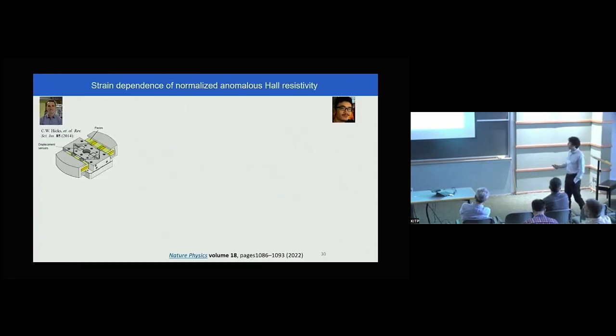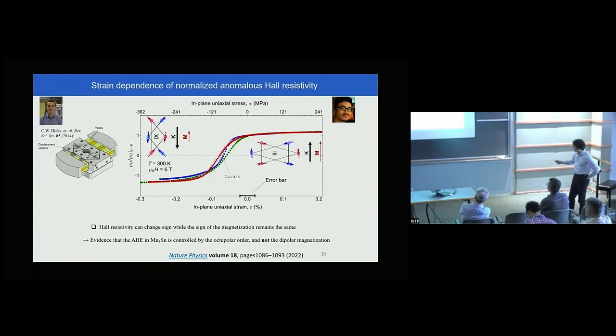Collaborating with Cliff Hicks at that time in Dresden, he moved to England, he developed this very nice piezoelectric cell, which allows us to go to tensile and compressive stress on both sides continuously, and within the elastic limit, we did this measurement very continuously without any problem, and reproducibly. And you can see that this is a renormalized Hall effect. The plus sign goes to the negative as a function of uniaxial strain. So this is exactly what you expect for the anomalous Hall effect dictated by the octopolar order, not by dipolar magnetization. So in other words, this strain could mediate the 180 degree spin rotation or reversal. Okay, this is for the strain control.